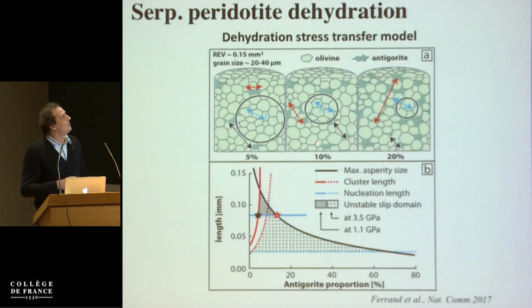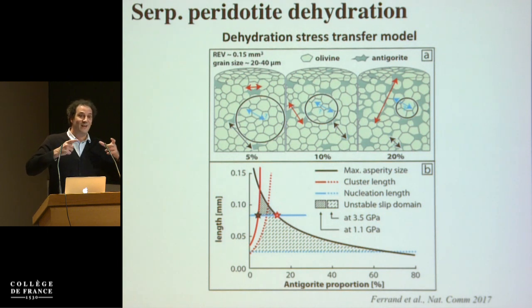Thomas Ferrand came up with an alternate model, which we call the dehydration stress transfer model, basically where you have a framework of hard olivine with some patches of serpentine, and as you destabilize these patches of serpentine, you transfer stress onto this big olivine asperity, and if you have enough dehydration, you will break the asperity, but the asperity also needs to be larger than the nucleation length, otherwise it will break aseismically.